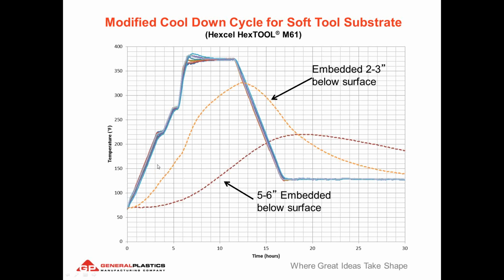So let me run that through again really quickly. As the temperature goes up, the graphite tool on top is really not expanding to any appreciable amount, but the foam will expand at a faster rate. So therefore, your graphite tool will gel and set shape at a higher temperature, which means the foam is larger than what was machined at room temperature. So you need to compensate for that difference in your tool design.